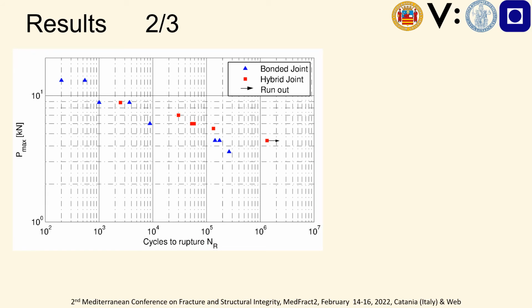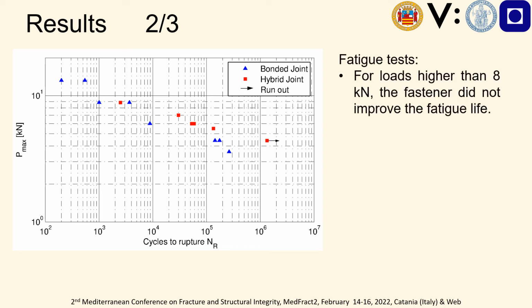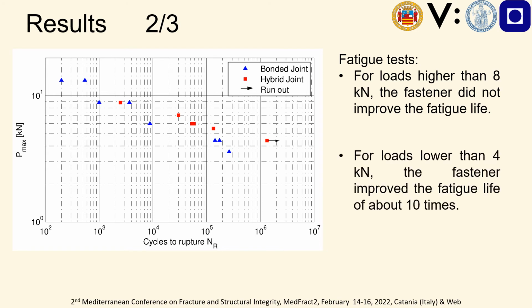Here you can find results related to the fatigue test. In particular, in blue you can find the points related to the experimental data for the bonded joint. In red you can find the points related to the hybrid joint, and with the black arrow you can find the runout for the test. And here you can observe that for high load, higher than 8 kN, the presence of the fastener didn't improve the fatigue life, whilst for lower load, lower than 4 kN, the presence of the fastener has an influence on the fatigue behavior of the joint, and in particular it improves the fatigue life by about 10 times.